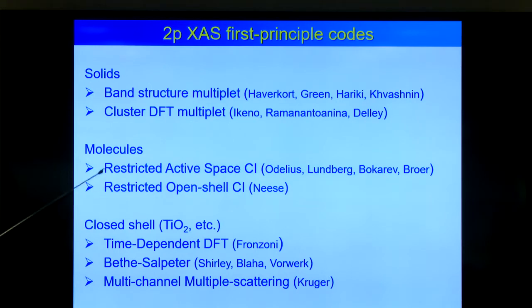For molecules, there are a lot of restricted active space calculations. They are all very similar, by Scandinavian groups. And Neese in Mulheim has a slightly different, okay, he's not in the audience, completely, but similar approach. So it's a configuration interaction on open shells for the X-ray. Then if you have closed shells, you can do all the direct extensions of DFT calculations, so time-dependent DFT or Bethe-Salpeter or multi-channel multiple scattering, and that works fine for titanium oxide, but it's not perfect for open shell systems. So there's a whole range of routes.